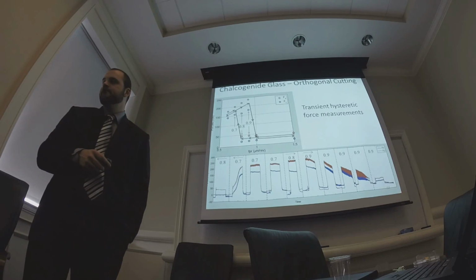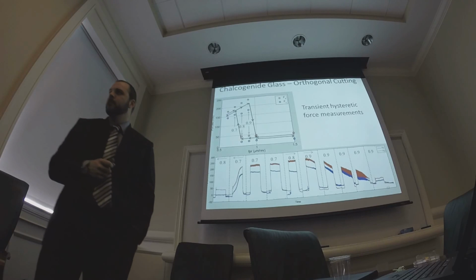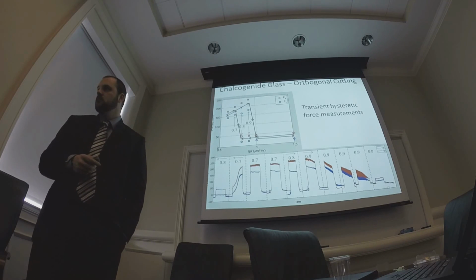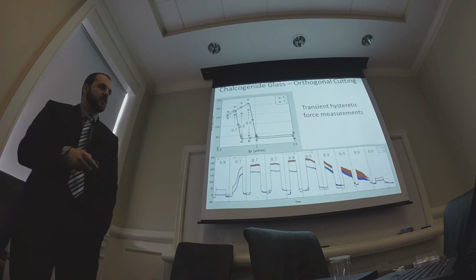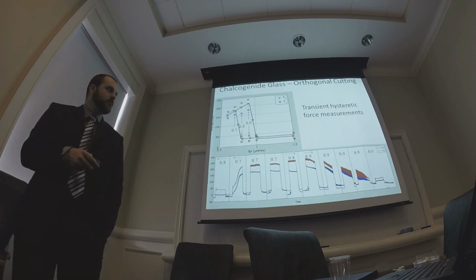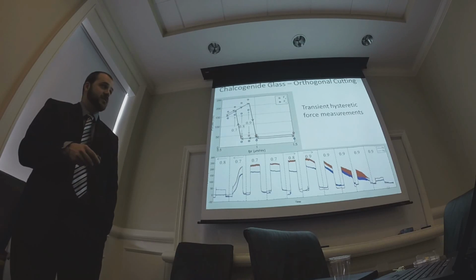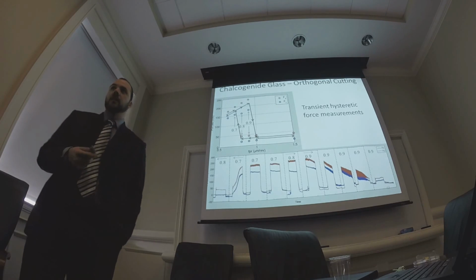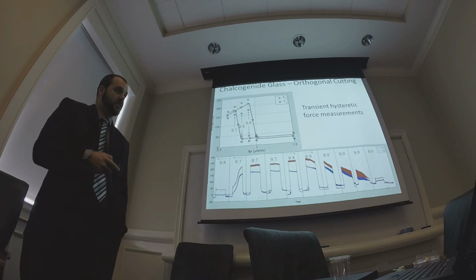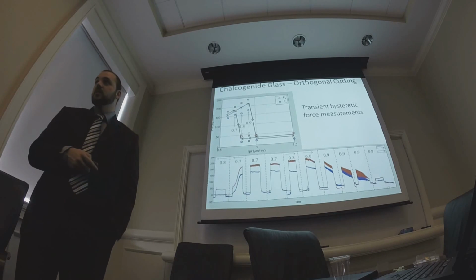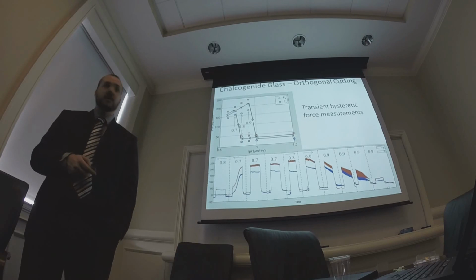The other thing we noticed was, in the region where it starts to drop, the force fluctuations even in the average force, the errors would jump higher up around that. So I wonder if it's actually, it could also be if there's some slight inhomogeneity. Since the material is unlikely to be perfectly homogeneous, this could be once-per-rev fluctuations as well. That would be interesting to zoom in on and see. I agree, that's interesting, I didn't see that.